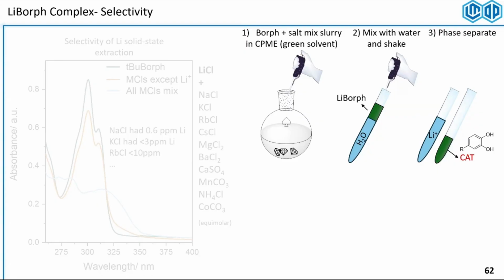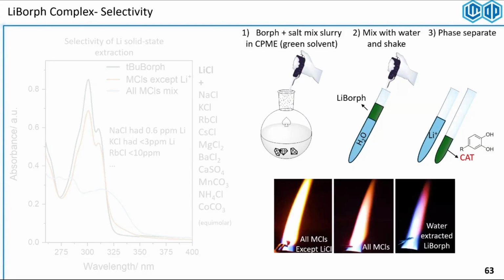so we can extract the lithium out of that mix of crystals that we had. And then we were hoping to get the macrocycle back, but what happens is the macrocycle breaks and proto-deborylates as soon as the complex touches water in presence of lithium. We think it's the acidity of the lithium that sort of catalyzes the proto-deborylation.